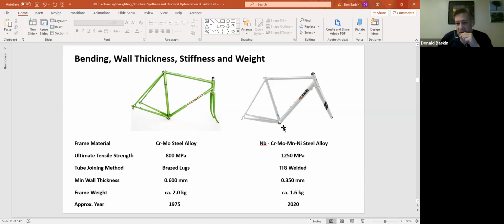In this case, the tubes are welded together using TIG, so tungsten arc welding. And in the top tube here, at the midpoint, the minimum wall thickness is 350 microns or 0.35 millimeters. Overall, this frame, including the fork, weighs about 1.6 kilograms. So in going through these 45 odd years, the bicycle industry, even using steel, has been able to dramatically reduce the weight of these bicycle frames by using materials and geometry. The materials modification here is the higher strength steel. Also, by looking at these two frames, you can see that the diameter of the tubing in the white frame, the Cinelli, is actually much bigger than the green Colnago frame. And so that's the geometry side of this. This effective geometry is going to be the focus of this lecture.